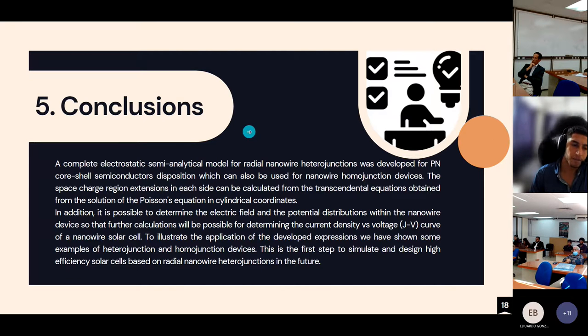Some conclusions. A complete electrostatic semi-analytical model for radial nanowire heterojunctions was developed for a PN core-shell semiconductor disposition, which can also be used for nanowire homojunction devices. The space charge region extensions in equilibrium can be calculated from the transcendental equations obtained from the solution of the Poisson equation in cylindrical coordinates. In addition, it's possible to determine the electric field and the potential distribution within the nanowire